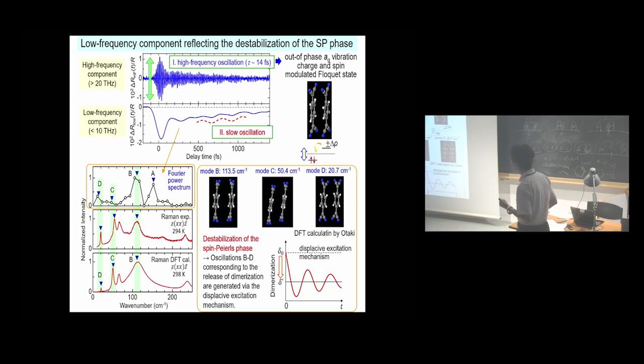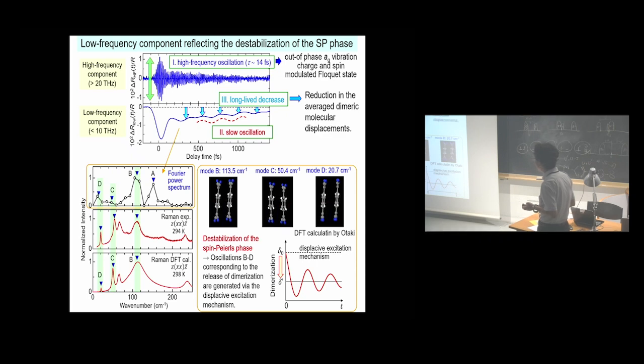oscillations of B to D, very slow oscillation corresponding to the release of the dimerization, are generated via the displaced excitation mechanism. The results also suggest that the long-lived decrease of the reflectivity is due to the reduction in the averaged dimeric molecular displacement. Note that during the presence of the out-of-phase ag mode vibration, like this, the spin-Peierls dimerization should remain destabilized for a long time. So that is the important point.